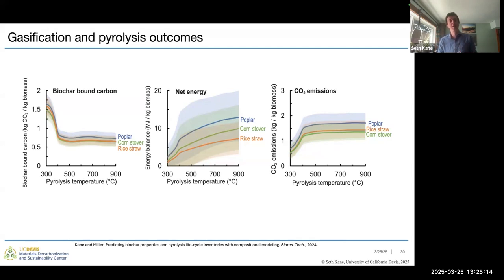This exact amount at lower temperatures is a little bit misleading because this is just at the factory gate. It doesn't account for degradation of that material over time. And we'd expect those lower temperature materials to degrade more quickly, whereas the higher temperature materials are quite stable over centuries. We also produce a little bit more energy as we increase that process temperature. This is a result of the hydrogen groups present in that biomass reacting off, and we're then able to use that hydrogen for energy, and our CO2 emissions stay pretty stable along with that bound carbon as we increase our temperature.